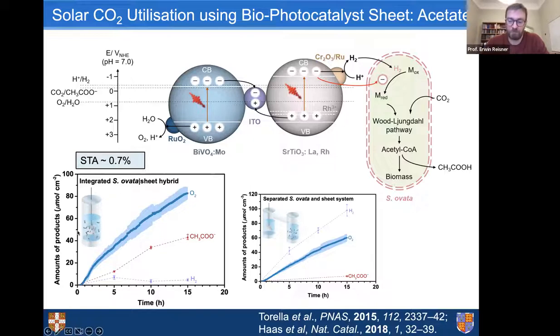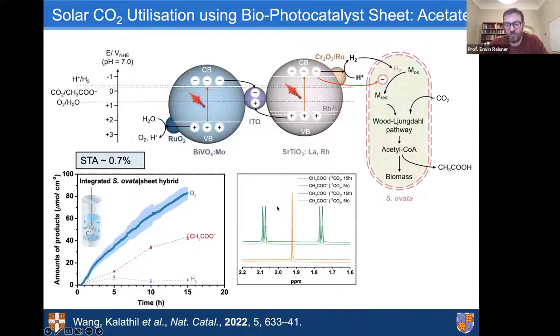everything together. And also here, the isotopic labeling is clean. If we have C12 CO2, we see a nice singlet of the acetate product in the proton NMR spectrum. If we label now the CO2 with C13, we have in the acetate 2 carbon 13s. This means our spin half proton needs to couple to 2 spin half carbons, which means we should see a doublet of doublets. That's exactly what we are seeing here, in the green trace.